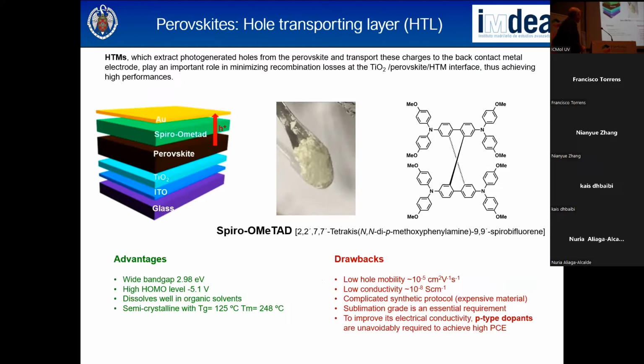So there are some advantages of this molecule. It's a wide band gap. It has a high HOMO level, which is important: minus 5.1 electron volts. It dissolves very well in organic solvents. This molecule is not planar, and it's semi-crystalline, with a glass transition at this value. This is an important feature, but there are many drawbacks with this molecule.